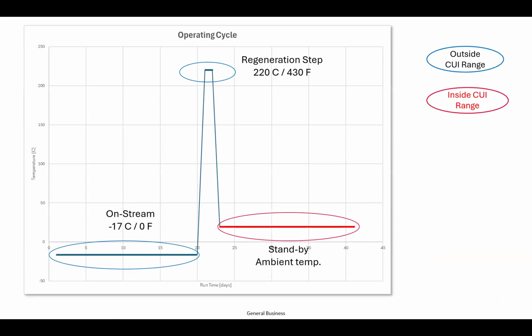You can see that if it operates in the low area, -17, or let's say 0 Fahrenheit, it's outside the CUI range. And if it's operating at the regeneration step, it's at 220 C or 430 Fahrenheit, which is also outside the CUI range. So it was not very well understood by the inspection department why it failed, because they thought it was only operating in 2 stages, and that was -17 and 220.